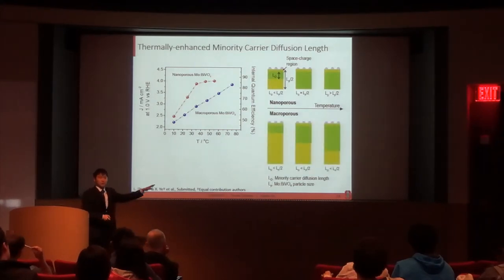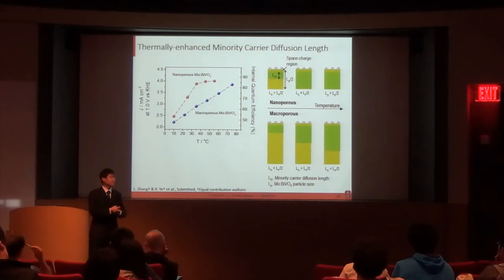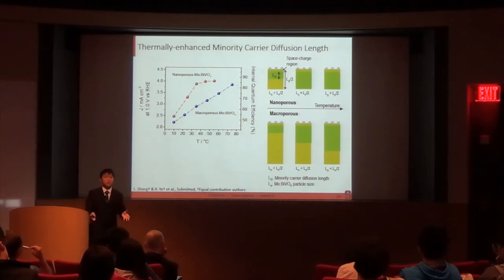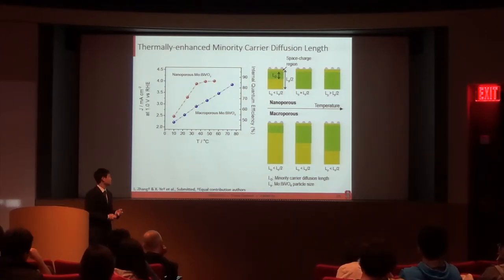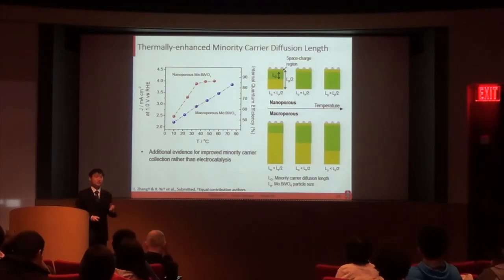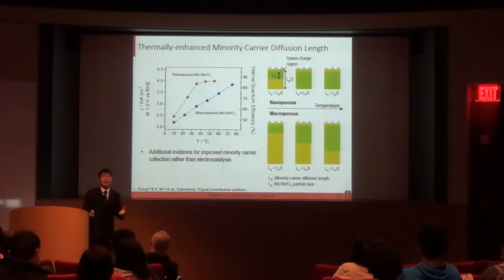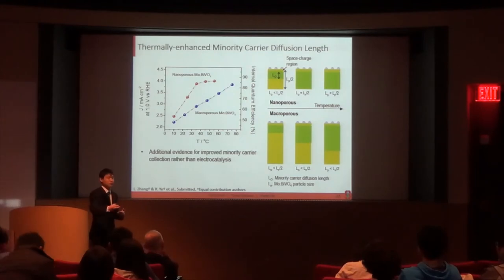However, for the macroporous BVO, due to the large particle size, the minority carrier diffusion length is always smaller than the particle size within the temperature range we investigated. So it never reaches a plateau, and that's why the photocurrent increases continuously. And that provides additional evidence that the thermal enhancement in the photocurrent could be only due to the improved minority carrier collection rather than electrocatalysis, because electrocatalysis should improve all the time.